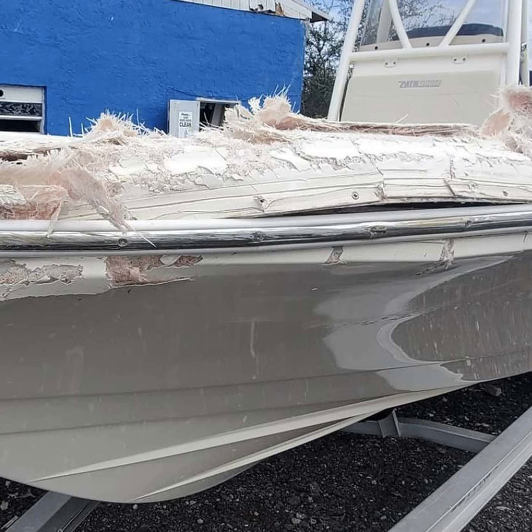So once you have all your grinding done, if you haven't maybe ground all the way through the laminate, but you're trying to figure out how much glass you need, you can span a mixing stick or a straight edge if it's flat, or something that has a little backbone but you can bend over it and it will maintain the profile. Then you can look at the gap underneath it over your bevel. If you can measure that with a micrometer, or slide something in between it, then you can get yourself a measurement of how much glass you need to add.